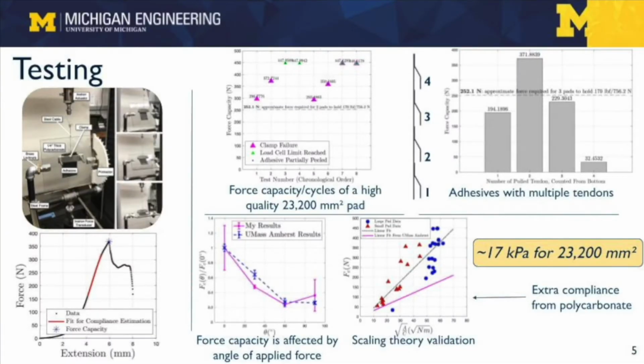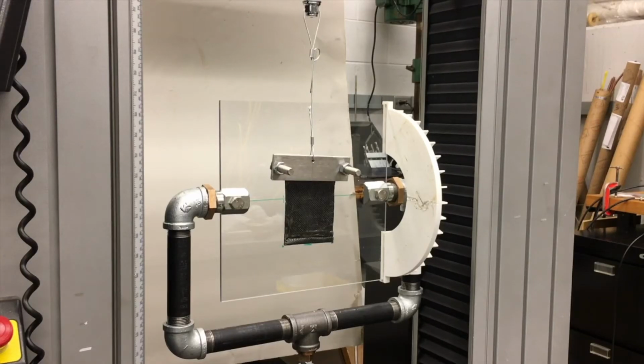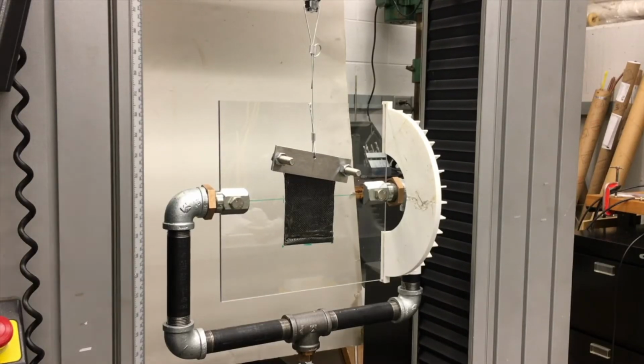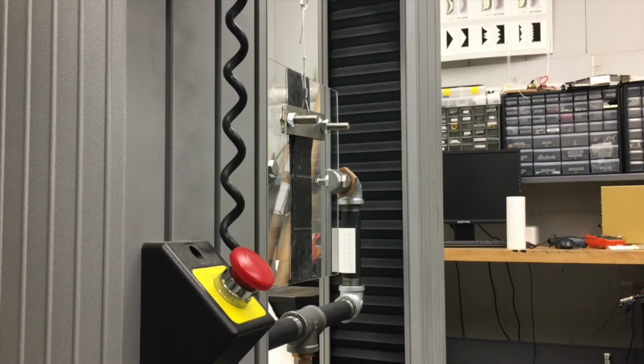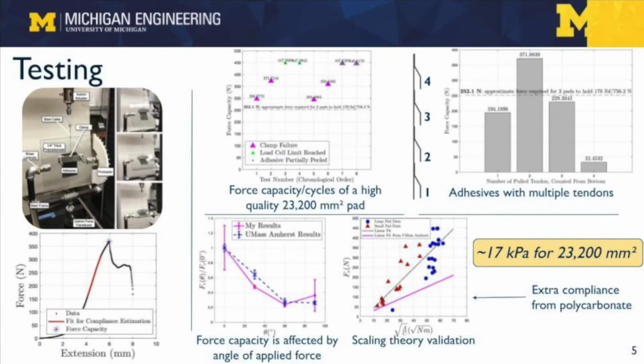So this is promising. I do want to point out that my testing setup was not perfect either. There were some instances where the clamp failed to hold onto the polyurethane surfaces of the tendons, and some instances where the limit of the load cell was reached at about 450 newtons, or about 100 pounds, before the adhesive fully peeled. There were also some tests where both of these things happened, so the experimental setup could be improved greatly.